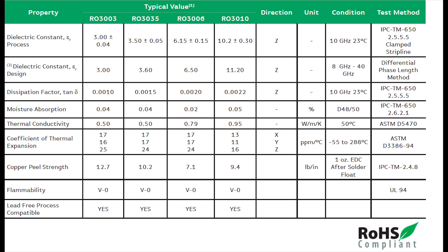The coefficient of thermal expansion, CTE, ideally should be at 17 parts per million per degree C. The rule of thumb is that as long as that number is 70 parts per million per degree C or less, that's considered pretty good. The CTE of all these RO3000 materials falls in a range that is extremely good. Peel strength is very good, the system is flame retardant, and all these materials are very robust to lead-free soldering processing.